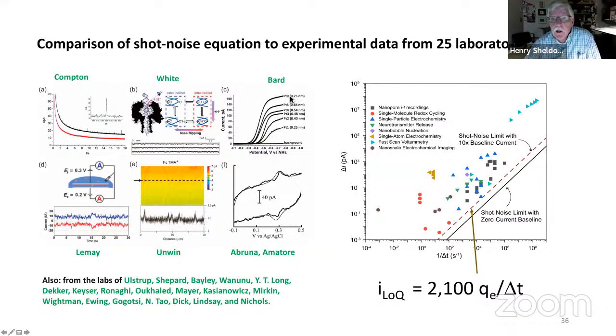And there's lots of things here, and in the Unwin experiment down here, they're mapping out the activity as a function of the structure of the electrode. Over here in the LeMay experiment, there's diffusion, there's redox cycling, but there's also evidence, by measuring the current and working through the analysis, that the molecule is not just redox cycling, but it's adsorbing for a very short time at the electrode surface. And when it's adsorbed, it's not diffusing, so the current decreases.